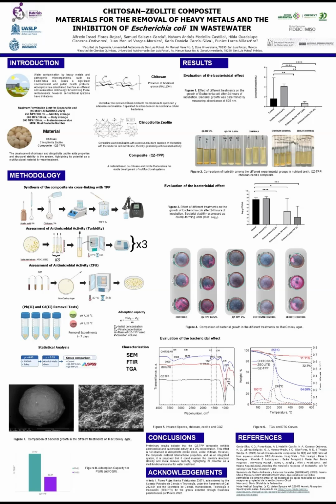These results also show that clinoptilolite, used as a control, did not exhibit a noticeable inhibitory effect against E. coli, as evidenced by the high absorbance values and CFU counts. These results confirm that the antimicrobial activity of the composite is associated with chitosan and not with the mineral support. In this context, the primary function of zeolite within the composite is to provide structural stability and act as an adsorbent matrix, while chitosan is the bioactive component responsible for bacterial inhibition.